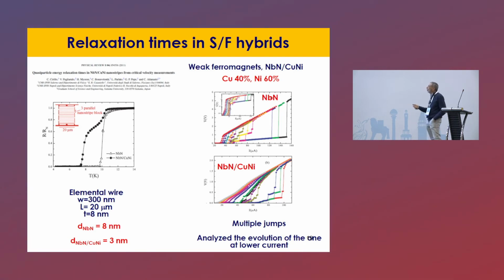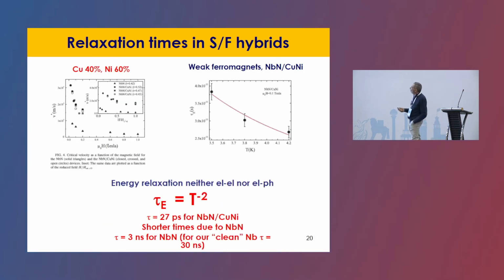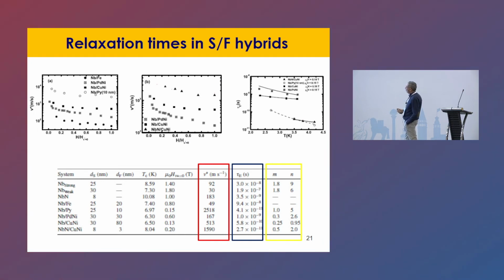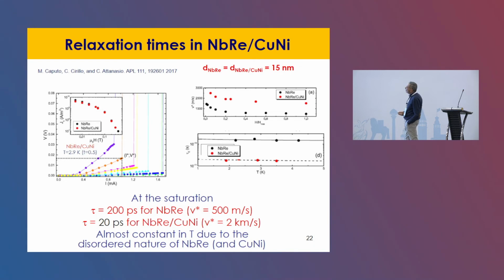Okay, we also did this with niobium nitride copper nickel. This is a more complicated layout of the sample that we measured. We have these phase slips here, but we just concentrate on the first jump at lower current, and we also obtain the same result. So as you see here, again niobium nitride, and higher velocity for niobium nitride copper nickel. So when you put a ferromagnet on top of your superconductor, we always see an increase of the critical velocity.